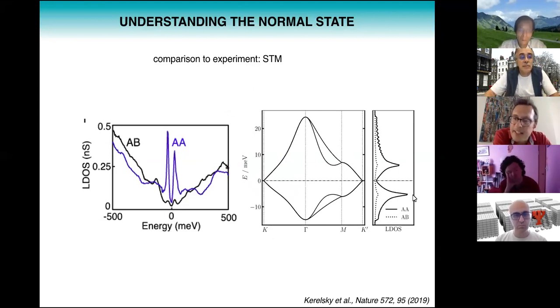And since the states at the endpoint are mostly localized in the AA regions, you get a big LDOS in the AA region and just a relatively minor one in the AB region. So this is basically consistent with theory, and what it tells you is that the separation of the Van Hove singularities, of these peaks, is basically a reflection of the band structure. So that's something that is very important to study.